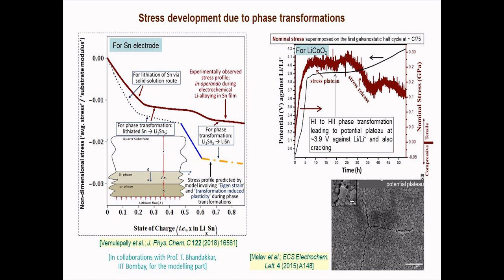So what you see here is a voltage plot, or a stress plot, from the measurement, and with the help of my collaborator from mechanical engineering, Tanmay, we could get it modeled and develop understanding of the degradation of tin based electrode during the electrochemical lithiation, delithiation, and we saw it is primarily during the phase transformation regimes where the cracking and plastic deformation cum cracking of the electrode starts taking place.